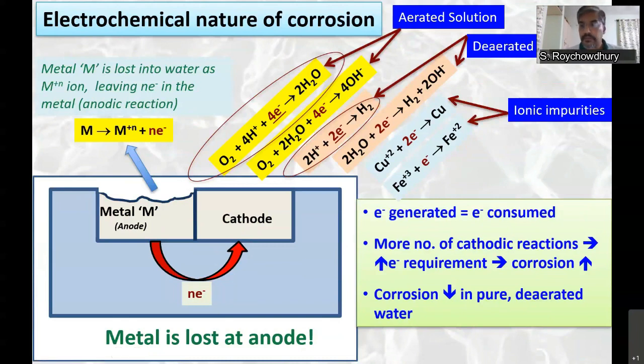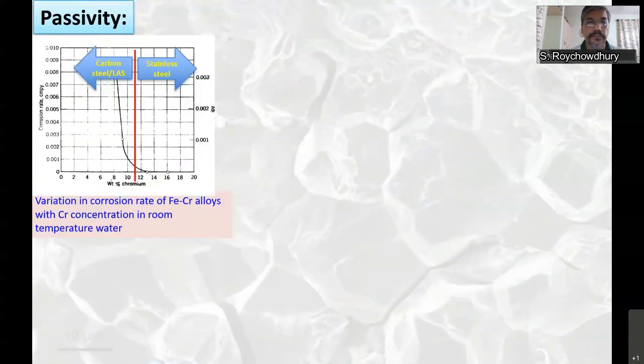So we straight away come to the first basic corrosion mitigation method: remove oxygen. In deaerated condition, if you remove oxygen, the corrosion rate comes down. Similarly, if you remove the ionic species, or if you use pure water, then also the corrosion rate will come down. Another important concept is passivity.